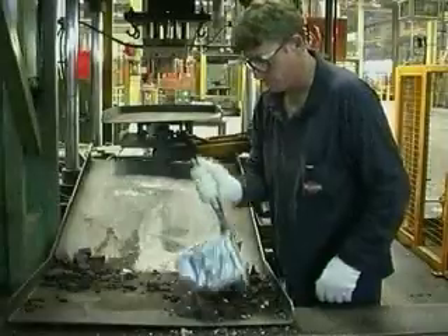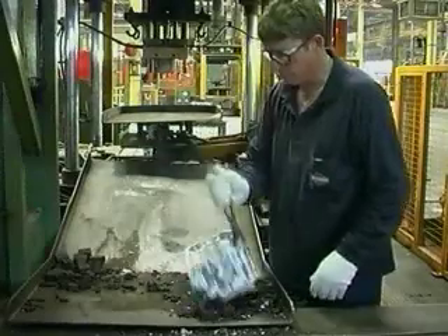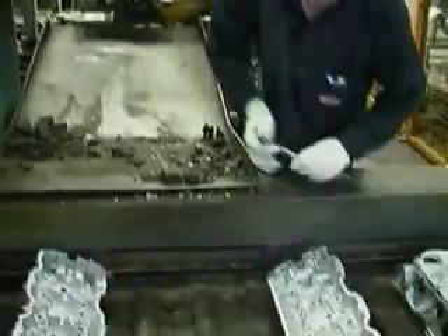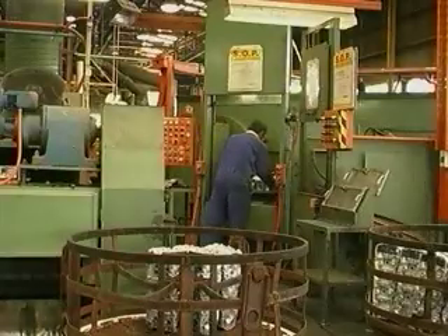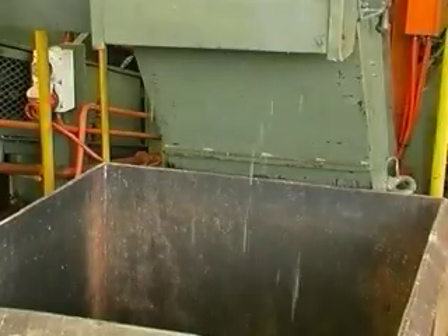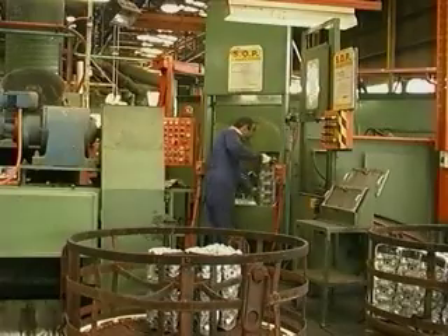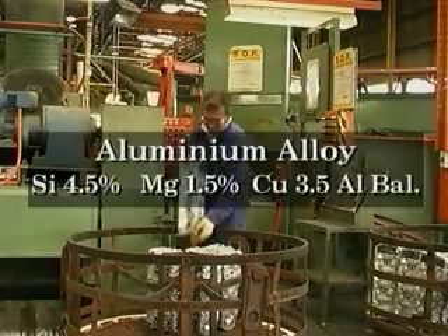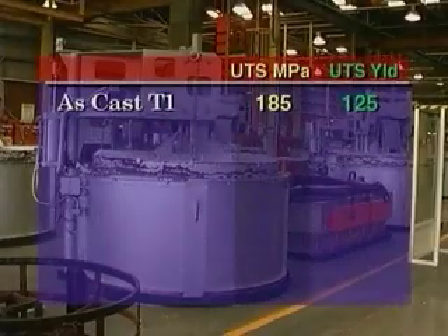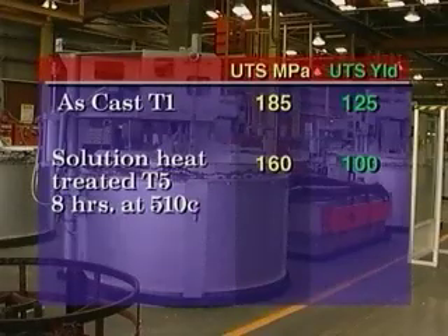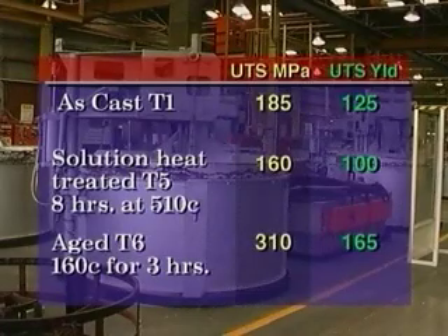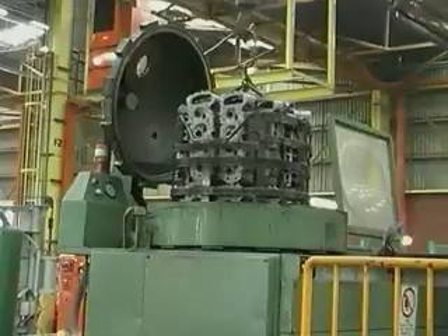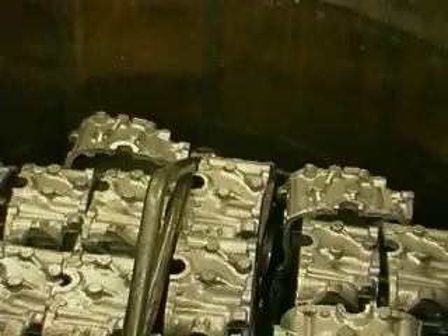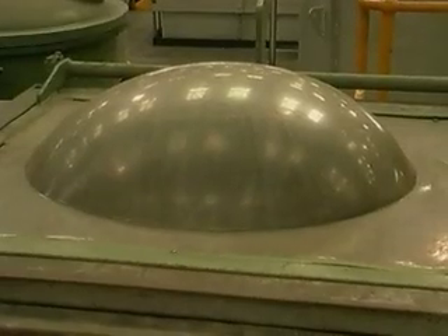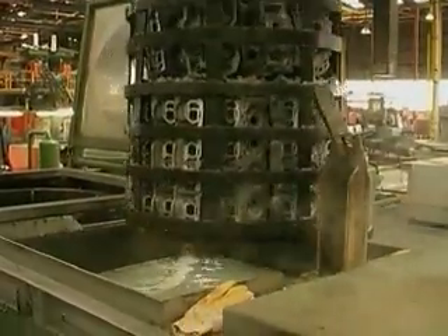Following visual inspection, the cylinder heads are allowed to cool slowly. After having their runner systems cut off, they are loaded into baskets for heat treatment. For this application, a heat-treatable aluminium silicon copper alloy is being used. To improve the strength of the cylinder heads, they are heated to 510 Celsius and soaked for 8 hours. They are then promptly quenched in water and reheated to 160 Celsius for 3 hours. This heat treatment greatly improves their mechanical properties. To ensure that all castings are 100% gas-tight, they are impregnated with a polyester resin that will seal any minor defects that might be present.